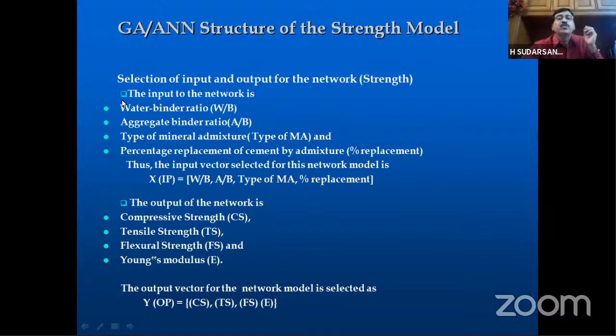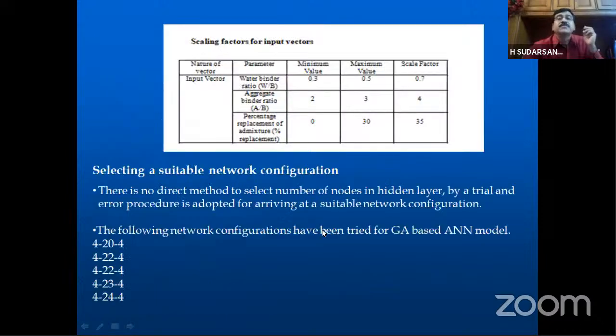So the input parameters are water binder ratio, aggregate binder ratio, the type of mineral admixture, whether it's fly ash, metakaolin, or silica fume, and their percentage replacement. All this becomes the input vector. I have given the input vector here. The output vector is compressive strength, tensile strength, flexural strength, and Young's modulus. So this is the strength model. Similarly, we have derived the durability model also.